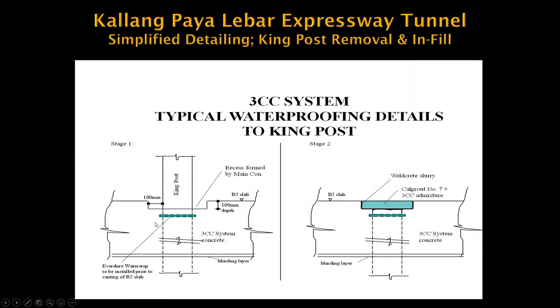There's a quick description of it. So this is the hydrophilic joint strip. It's wrapped around the king post. After completion, it's just cut off, and the gap at the top of it is filled with a non-shrink grout containing an HPI additive.